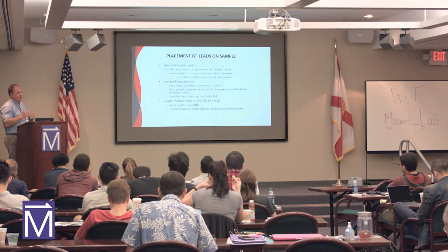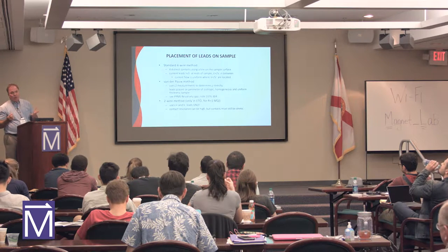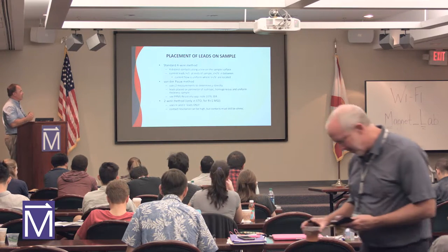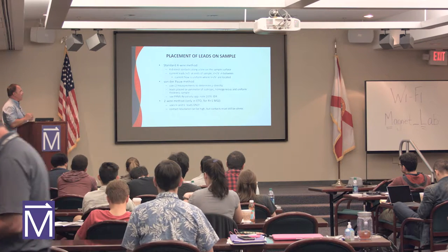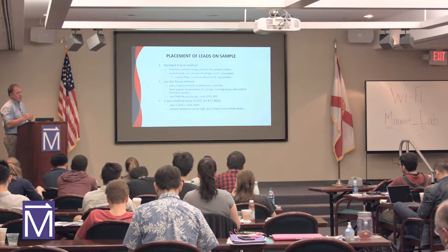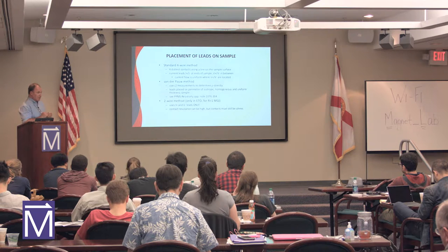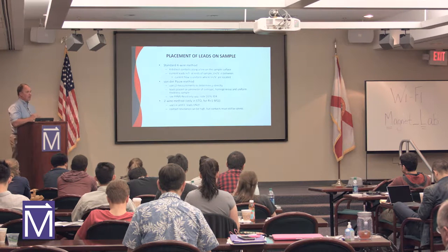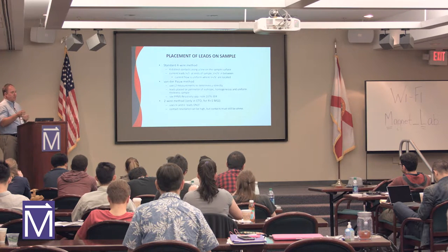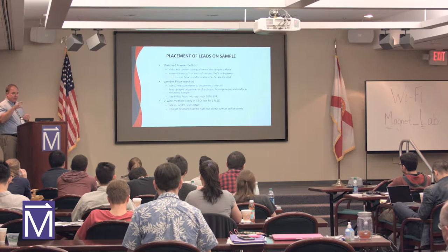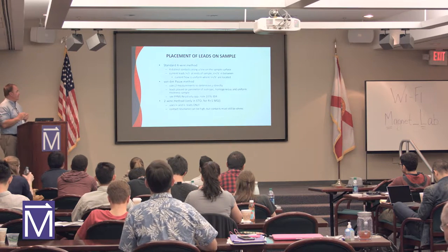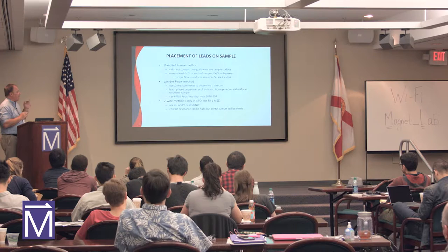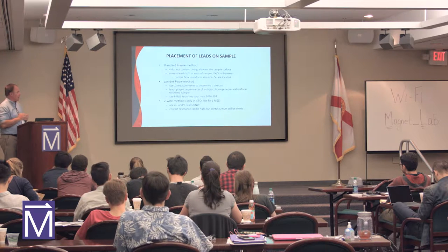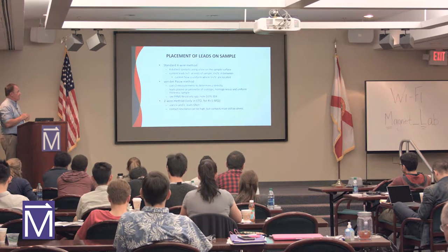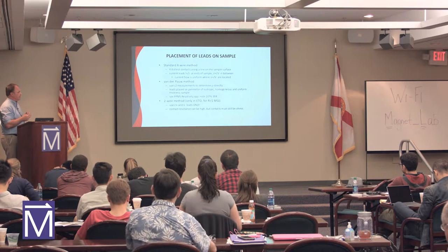How do you place the leads on the sample? Well, that's the type of measurement you're going to do, four wire measurement. You've got the contacts on the pad, Van der Pauw measurement, so you can put your connections on the perimeter of the sample, and then you're going to take multiple measurements on those contact points, and you can get resistivity directly on that. We've got a nice application note that talks about the Van der Pauw method, two-wire method.